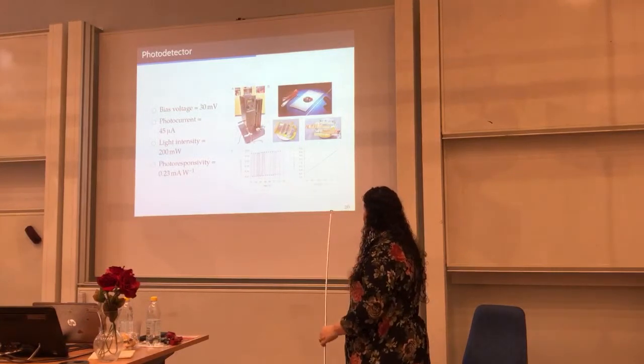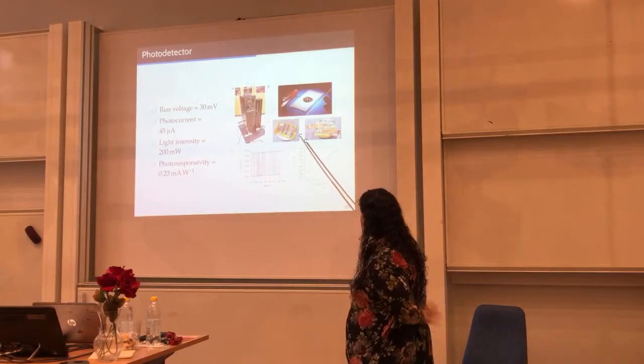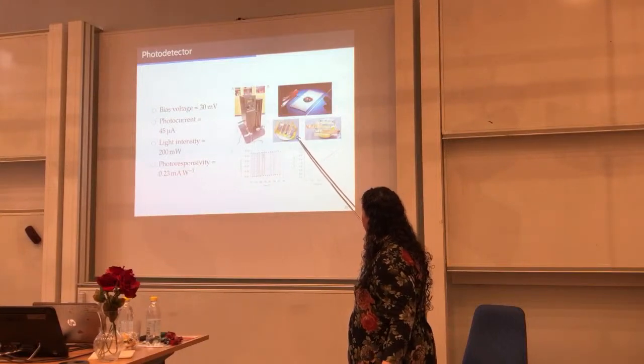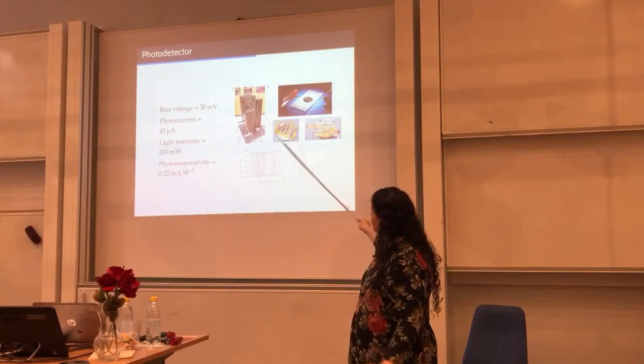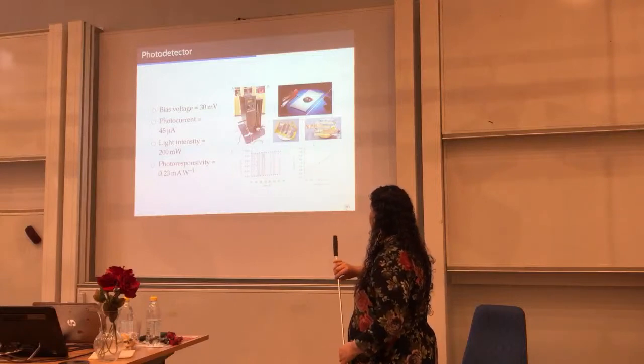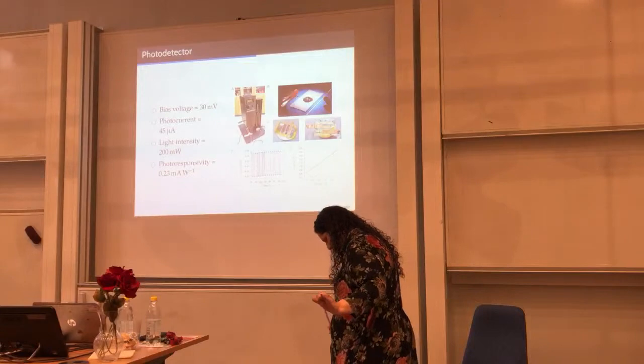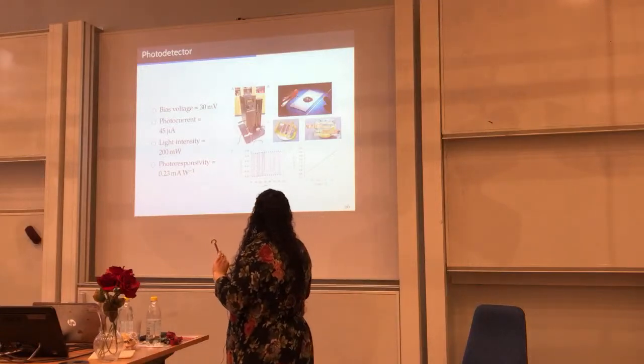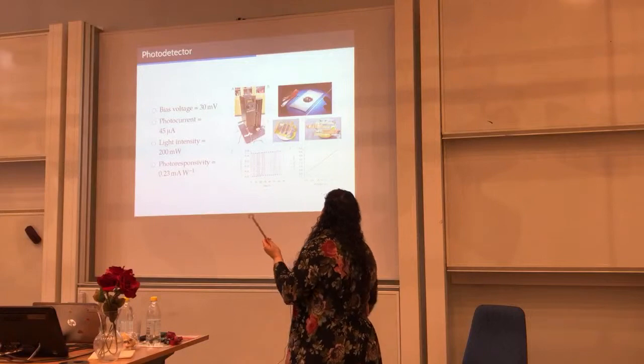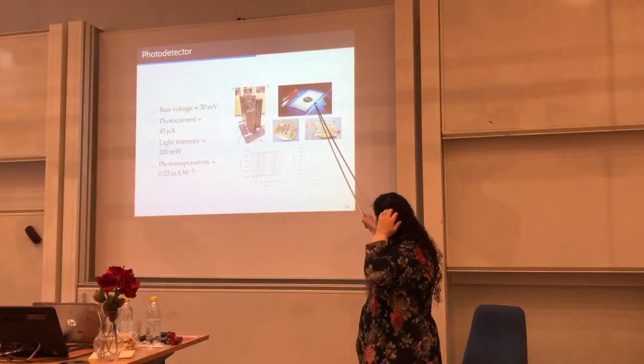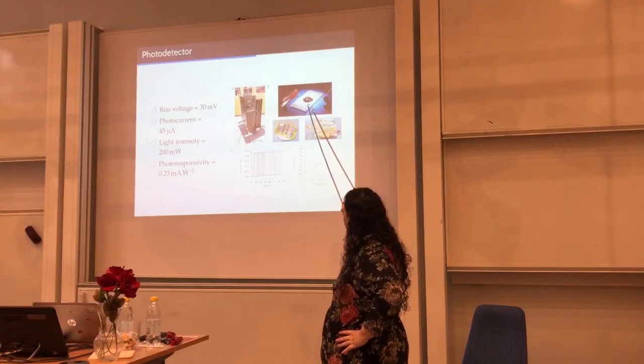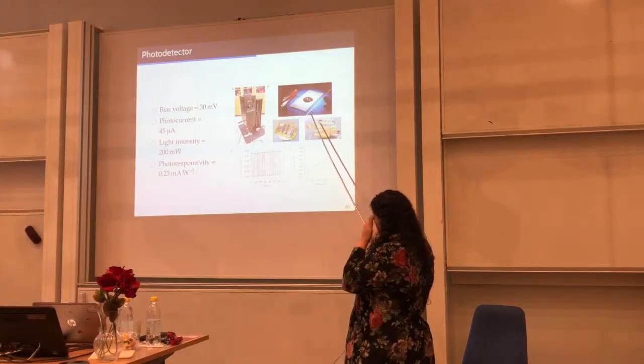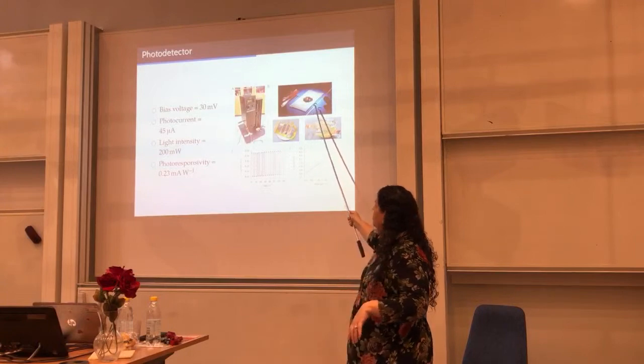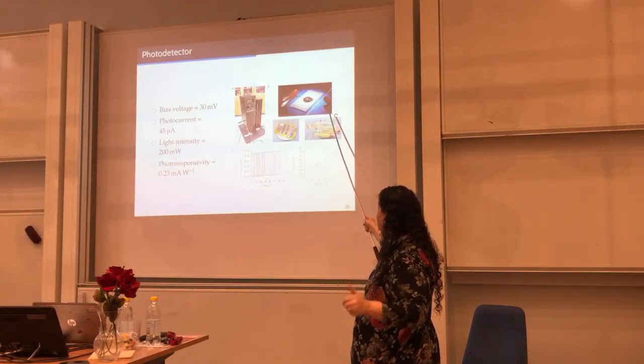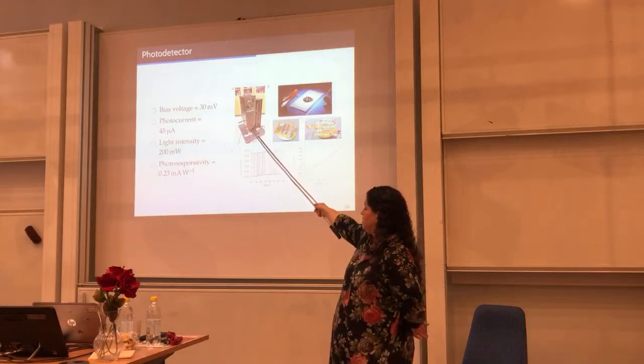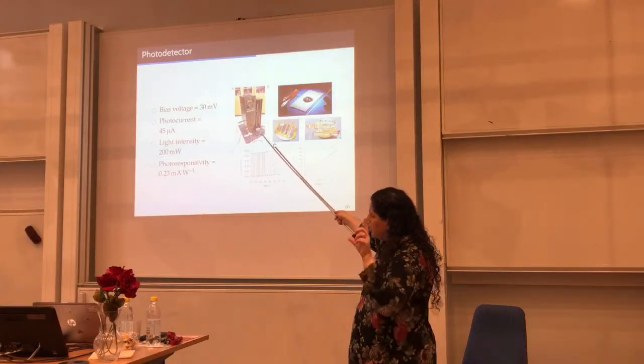dispersions. So what I did is that I deposited this on a polyimide plastic, and I put some gold on top to flow the electricity through the material, and then you shine light on it. Initially, these were the experiments that Magnus Humegård and I did. We put the flake on a glass slide, and then we have some gold wires to measure the photoconductivity using this solar simulator, solar energy, sorry.